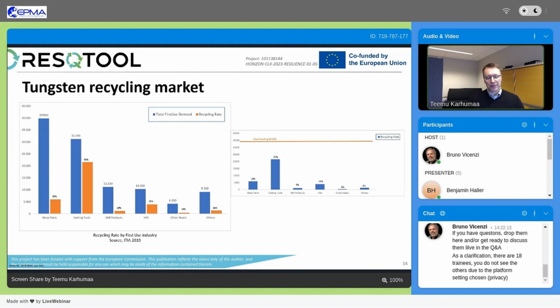And for the rest, mill products, meaning pure metallic tungsten products or tungsten heavy alloys, the recycling rate is very low. And for high-speed steel, it's a little bit higher, but in general, cutting tools, as we can see in the picture on the right, when all this scrap is collected globally, 34.5 thousand tons, out of that cutting tools cover more than 60%. So in the wear parts, there is huge room for improvement in terms of recycling.